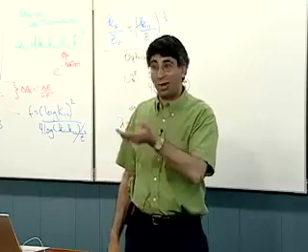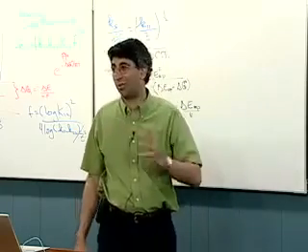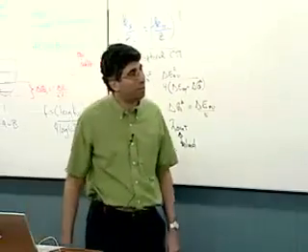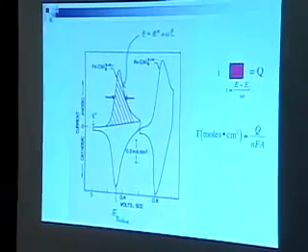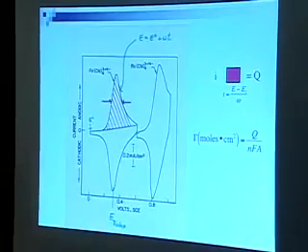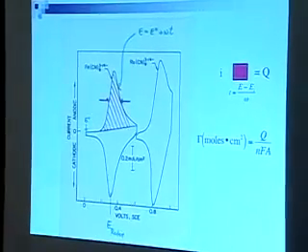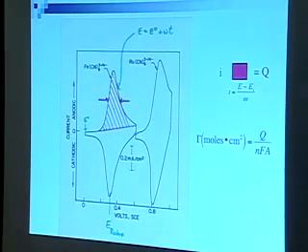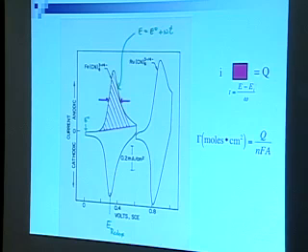And as long as you're happy knowing your redox potential to within 20 or 30 millivolts, you're in good shape. So we get our redox potential by taking the halfway potential between these two peaks, which is 0 in this particular case, but not always on a surface because of these parameters and IR losses on the surface. We measure the peak-to-peak separation there, which turns out to be 90 millivolts, which suggests there are no nearest neighbor interactions in this particular case.